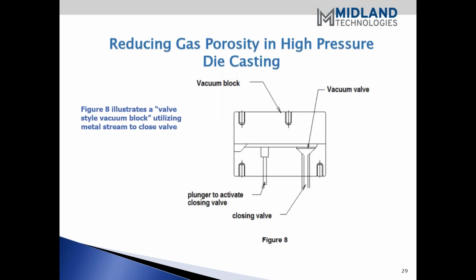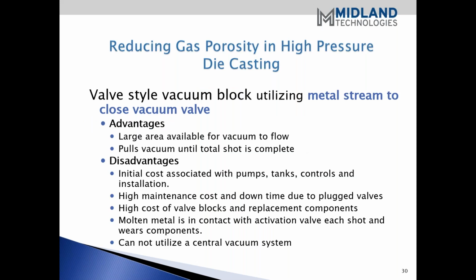So the other type of valve block is using the metal stream to close the valve. And in this illustration, there's a plunger in there that will be activated to close the valve. So a valve vacuum block using the metal stream to close the valve. A couple of advantages. Again, there's a large area available for vacuum to flow, and it pulls the vacuum until the total shot is complete.